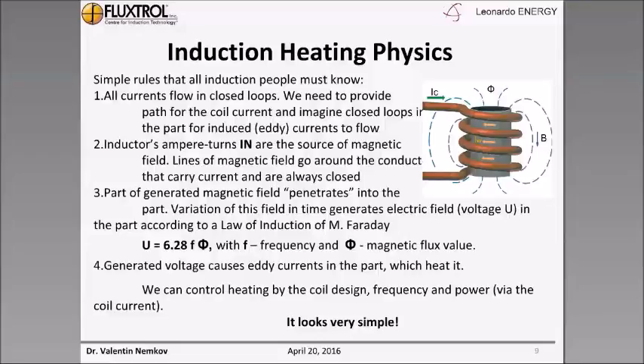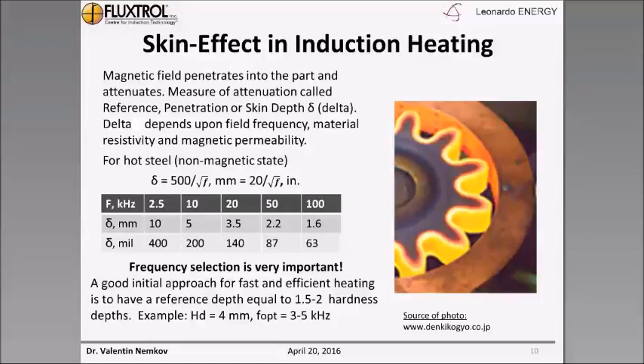It looks very simple, but maybe not so simple, because the materials that we heat may be magnetic. In automotive parts, they are almost all magnetic, and the phenomena in penetration of electromagnetic field in magnetic materials are rather complicated. In general, magnetic field penetrates into the part and attenuates. There is a certain legend and myth that the current inside of the part changes from the surface according to an exponential law. This could be true in some cases, but not always. And I'll show you later what really happens when heat treating automotive parts, surface hardening.